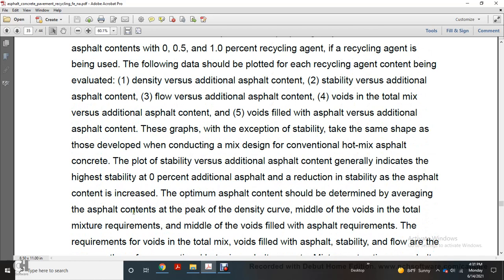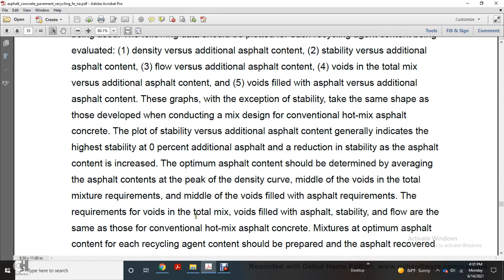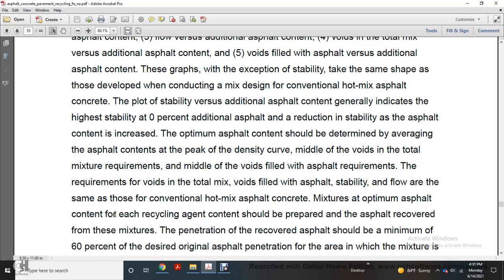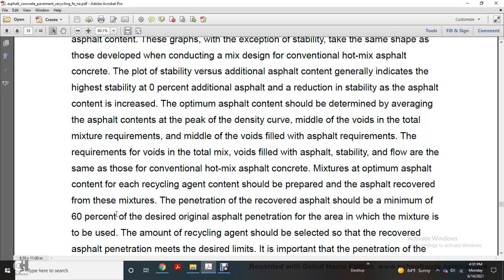The graphs, except stability, would take the same shape as those developed in conducting the mix design of conventional hot mix asphalt concrete. The plot of stability versus additional asphalt content generally indicates the highest stability at 0% additional asphalt, with reduction in stability as asphalt content is increased. The optimum asphalt content should be determined as the average asphalt content at the peak of the density curve, the middle of the voids in total mixture requirement, and the middle of the voids filled with asphalt requirements. The voids in total mix, voids filled with asphalt, stability and flow are the same as for conventional hot mix asphalt. For the mixture at the optimum asphalt content, recycling agent content should be prepared with asphalt recovered from these mixtures.